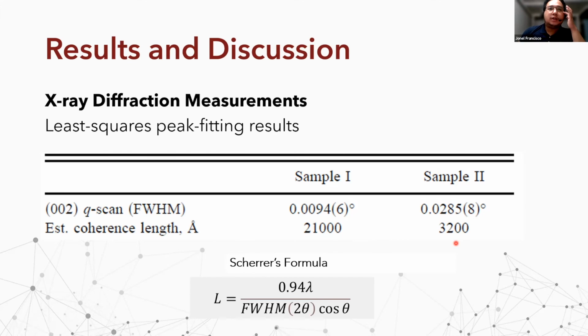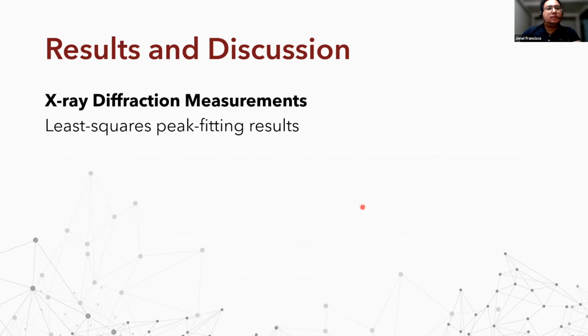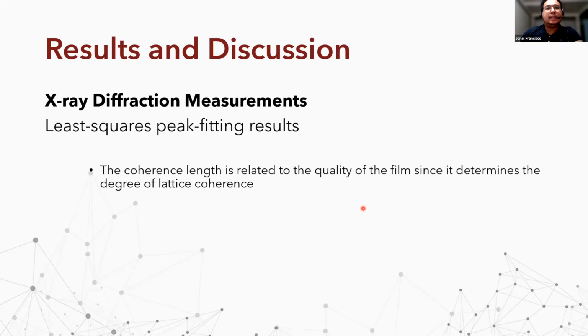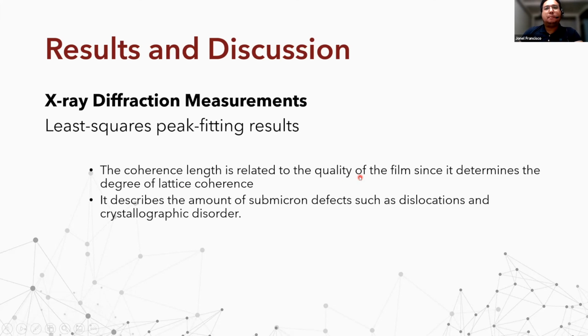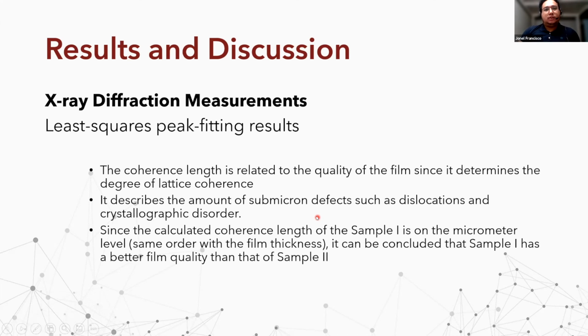What do these values signify? The coherence length is related to the quality of the film since it determines the degree of lattice coherence. It also describes the amount of submicron defects such as dislocations, and crystallographic disorder. Since the calculated coherence length of sample 1 is on the micrometer level, that is the same order as the film thickness, it can be concluded that sample 1 has a better film quality than sample 2 in terms of its out of plane measurement.